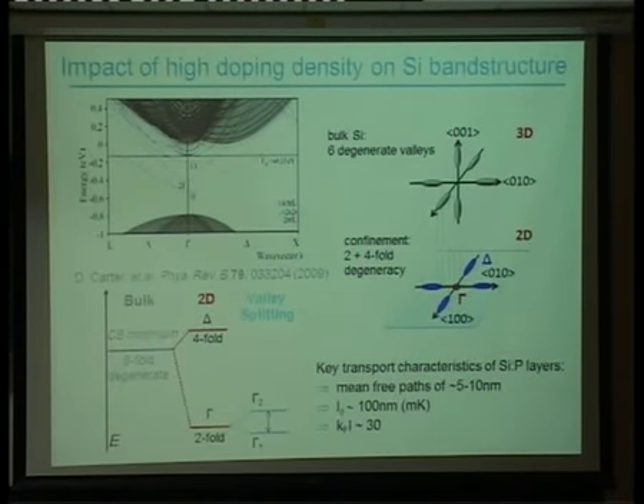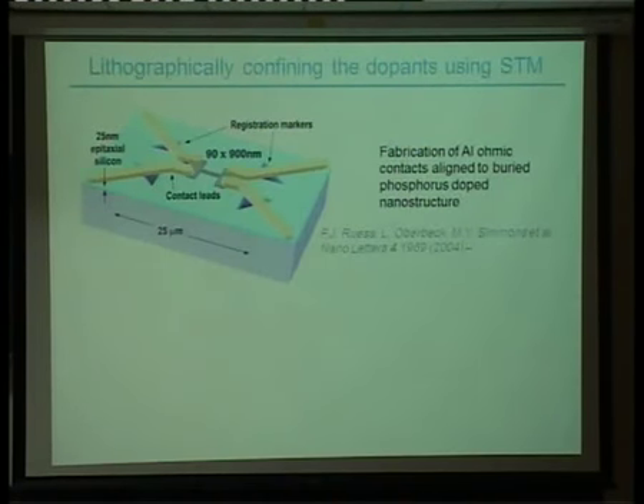And because of the high doping density, essentially the electrons are screening the potential charge of the positive phosphorus atoms beneath them. So it's unlike any kind of highly conducting system. It's like a dirty metal. So now what do we do? We come along with our STM tip, and we're going to pattern those phosphorus atoms into the surface in any kind of structure that we want, all the way down to atomic scale.